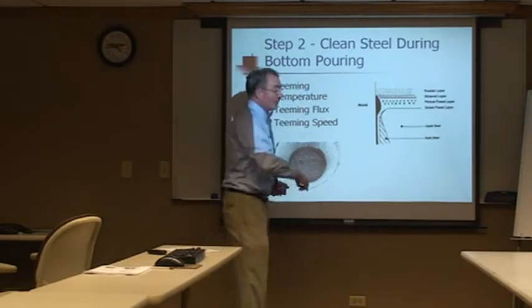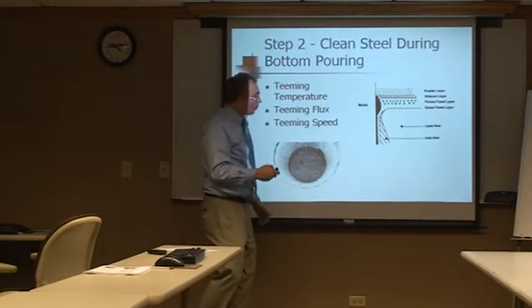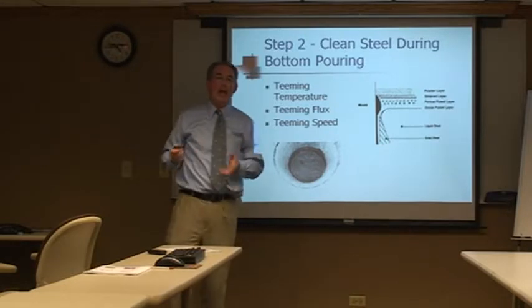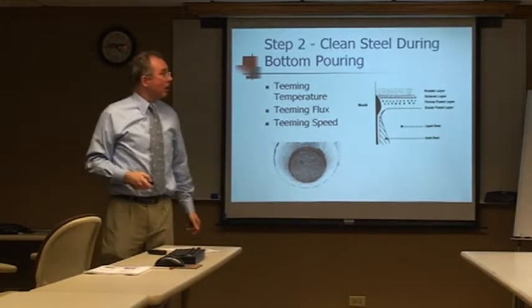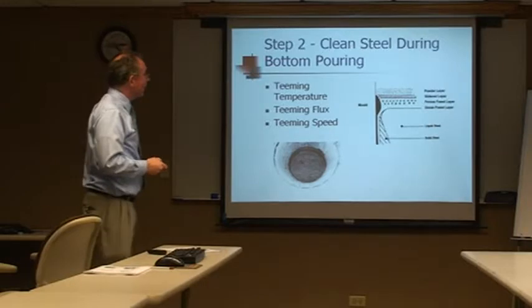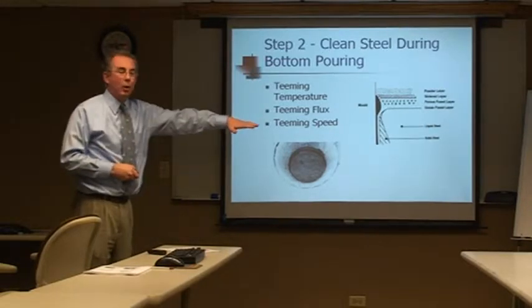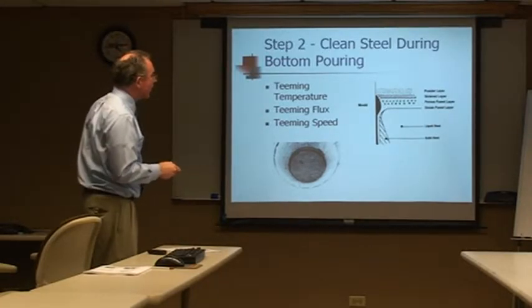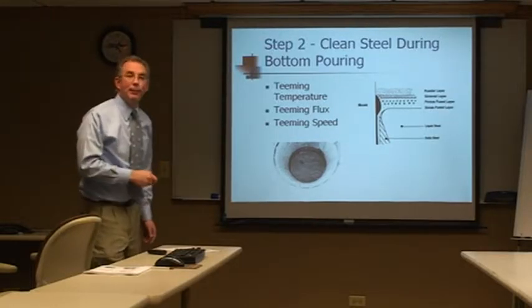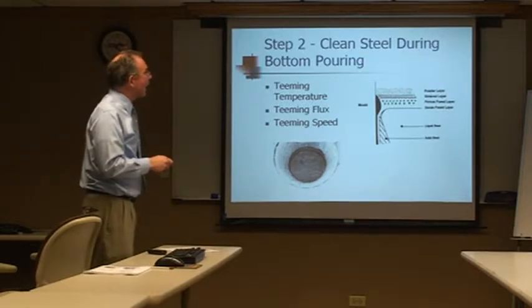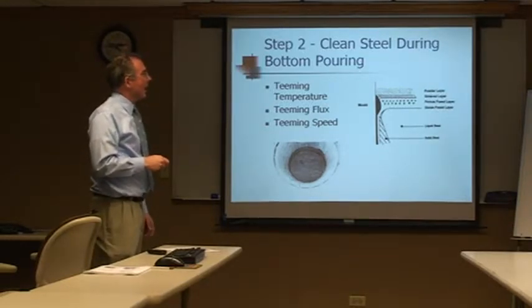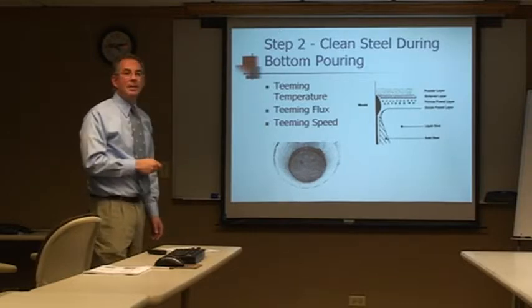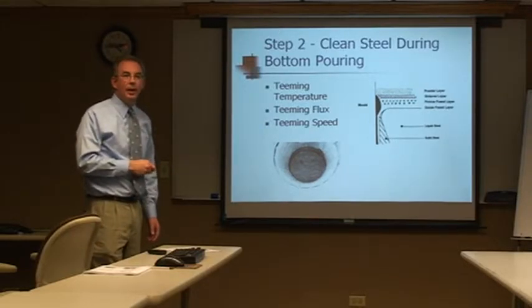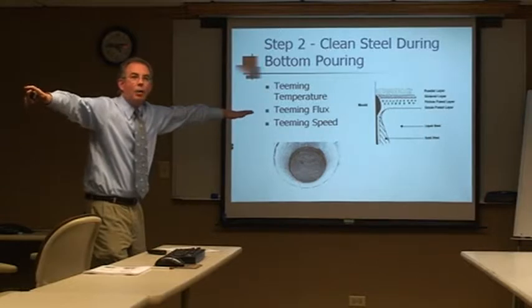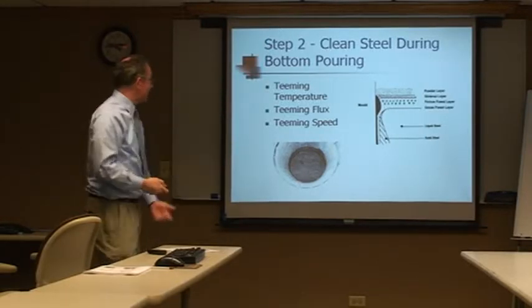And then when the steel comes down into the mold, we put this special flux. It's a fly ash-based black powder called teeming flux. This teeming flux is sitting on the bottom of the mold, and when this hot liquid steel, that's what this clear area is here, hits it, the heat from the steel causes this black powder to start to sinter. And as it sinters, it ends up becoming almost a glassy lubricant. And it spreads out over the entire cross-section of that rising liquid steel in the mold.